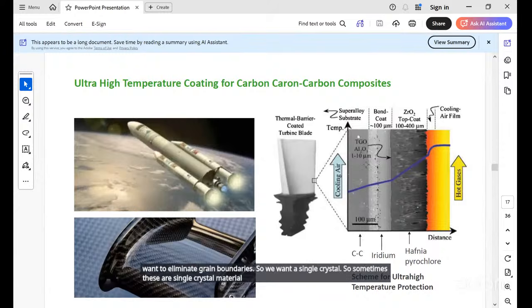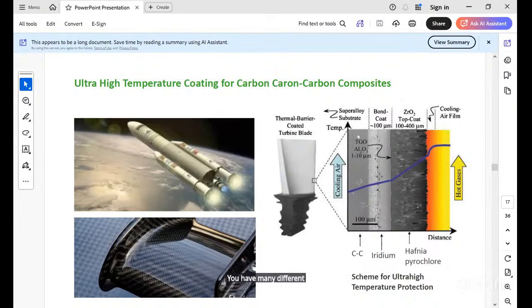So sometimes these are single crystal material. But for surface, you have many different layers of coating for different materials. So this was one of my first projects, to have coatings for carbon-carbon composite material, because carbon-carbon composite can be very strong even at 2000 degrees C. But in air, at that temperature, they will burn. So they will completely oxidize. So we were looking for making coatings. So I applied some ceramic coating, different layers and all that. Very, very advanced project from US Air Force. So that's what I'm showing here.